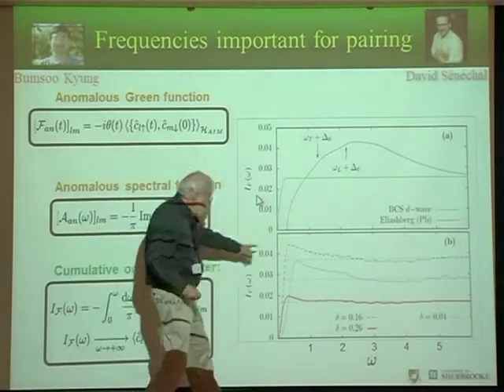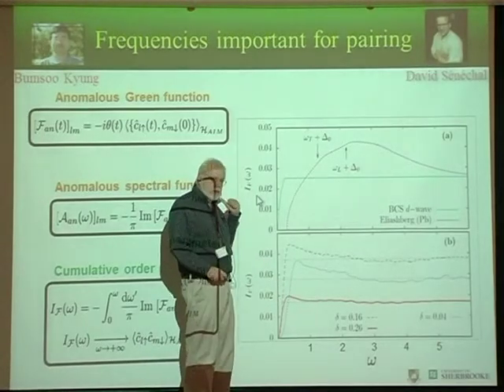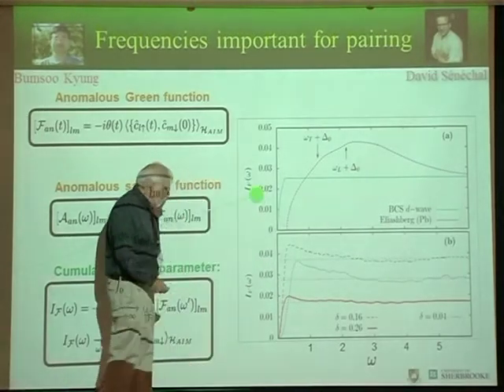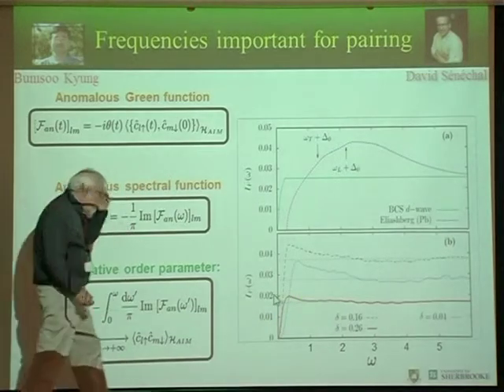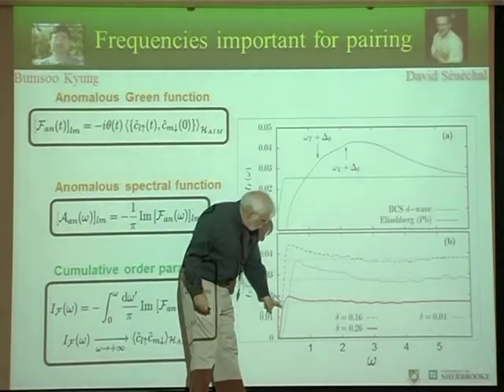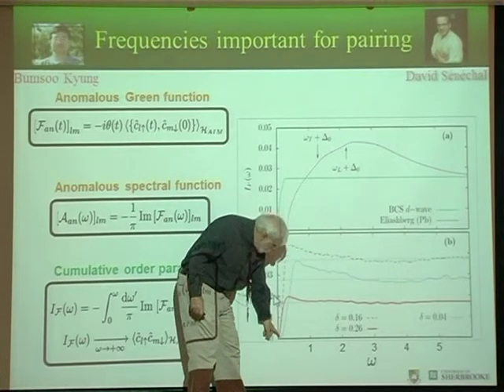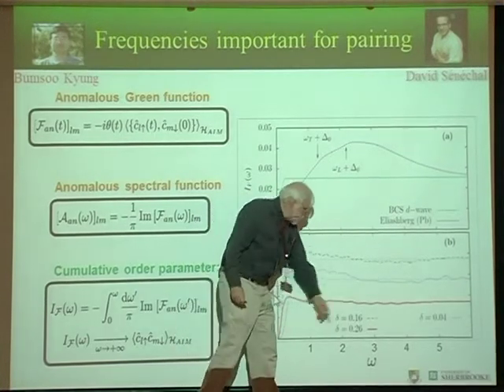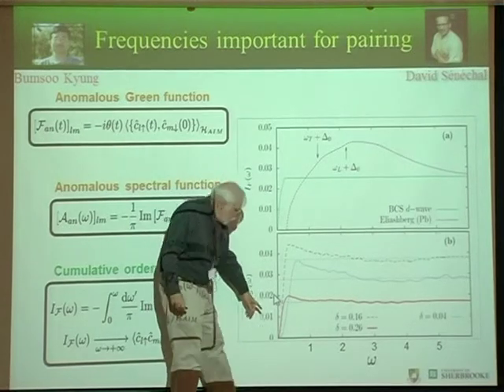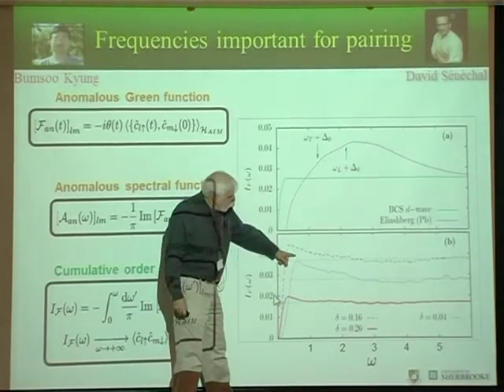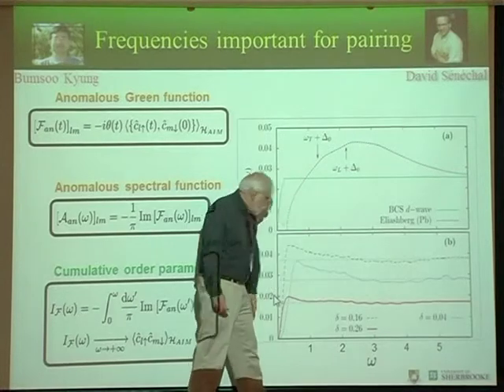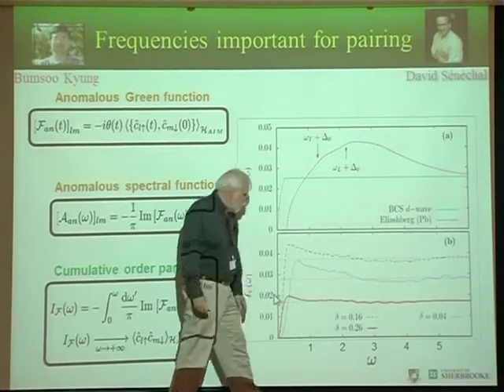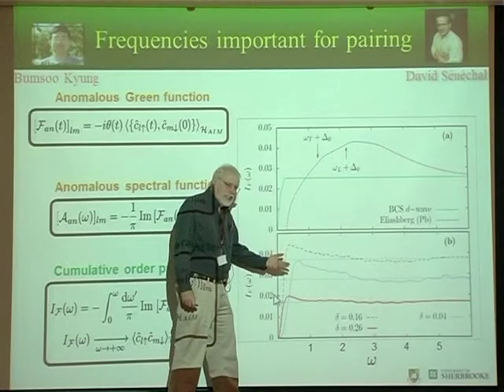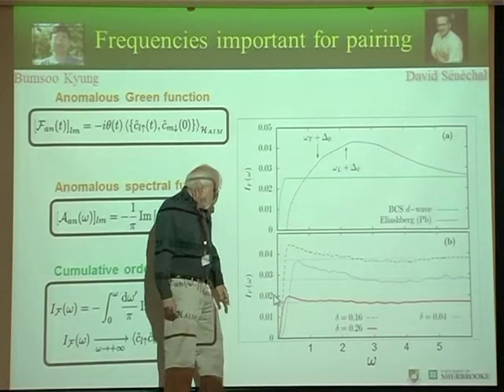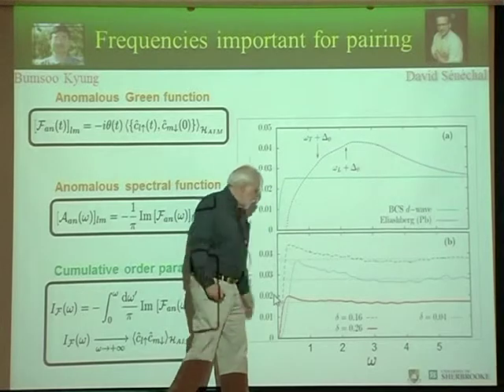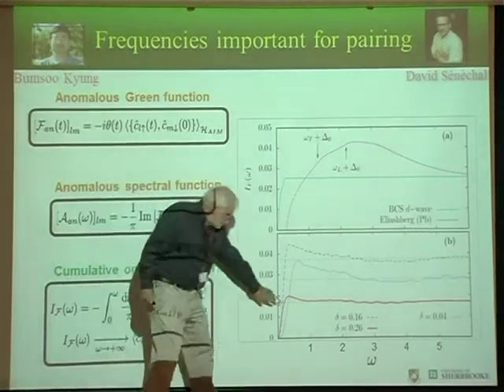So this is the result of the calculation for the phase diagram I showed you earlier. If you look at the overdoped system, it looks a little more like BCS. It goes up, and then it's almost flat immediately. In the underdoped region, that's this line, it overshoots more before it comes back. So as you get closer to half filling, repulsion has some effect at high frequency. And this is the optimally doped case. If you look at this scale, it's of order J.